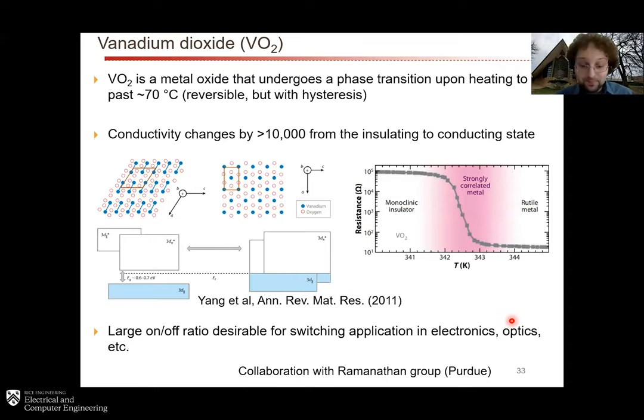So in my group, and even before that, when I was a PhD student in Federico Capasso's group, going back now 7 or 8 years, we've done a lot of work in collaboration with Shriram Ramanathan's group and some others on the use of complex oxides to do just this. So here's an example of the most famous complex oxide that has temperature tunable electronic and optical properties, vanadium dioxide, which when you heat it up past about 70 degrees C undergoes a dramatic, enormous phase transition, which changes the crystal structure, and this is of course reversible, the band structure, the electrical resistance, and also the optical properties.